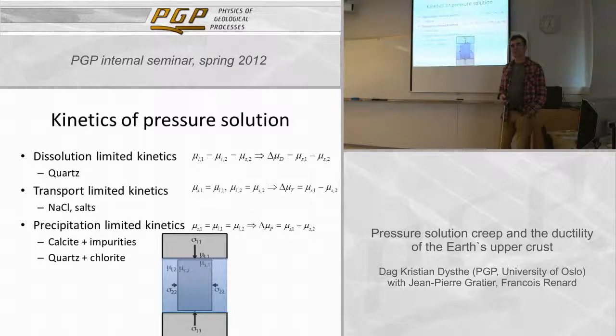And for different materials, different steps are rate limiting. Quartz is a material that dissolves very slowly. Quartz is very, very far from equilibrium at the surface of the Earth. You've got water with no quartz flowing over it, and still it will take an enormously long time to dissolve these glass windows or quartz in nature, and that's because the dissolution takes a much longer time.